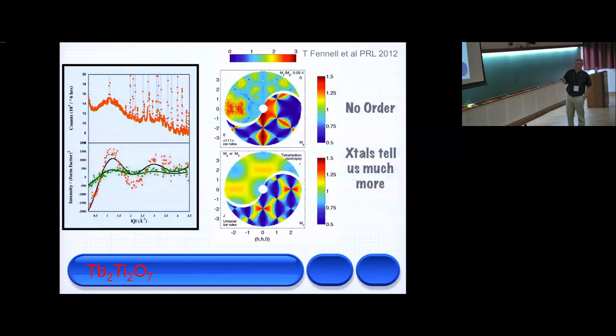These bumps tell us about the correlation. So in this case, it told me that there were 4.6 angstrom correlations between spins, and they would get sharper in temperature if that got longer. And we never see that. It always remains at this broadness. If you warm up, it gets flatter. In a real paramagnet, it should be background and very flat.